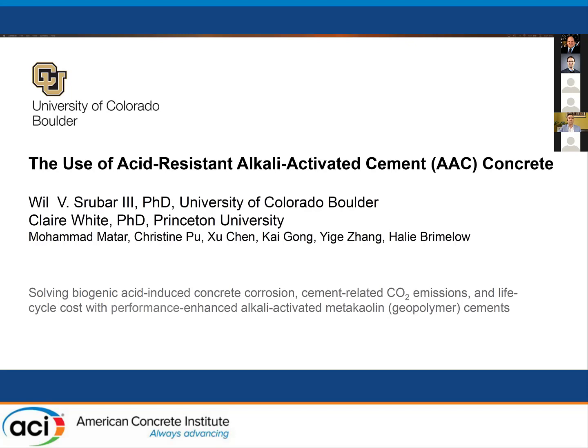For those of you unfamiliar with geopolymer cements, geopolymers really is a term that describes a subset of alkali-activated cements in which we use an aluminosilicate that is not fly ash or slag, but rather a calcined clay, such as metakaolin, that is really low in calcium or even calcium-free in our case, which is really mechanistically the key to its performance in sewer environments, as I'll explain in a few minutes. We produce these geopolymers by activating metakaolin with an alkaline activator like sodium hydroxide supplemented with sodium silicate. So unlike ordinary Portland cement, where you get calcium silicate hydrate and calcium hydroxide as the reaction products, geopolymers really produce predominantly a sodium stabilized aluminosilicate hydrate. And so there's really no calcium in the system.